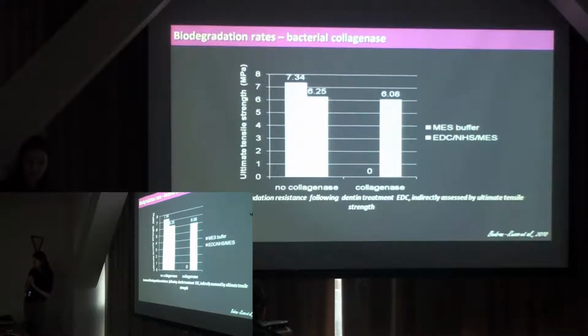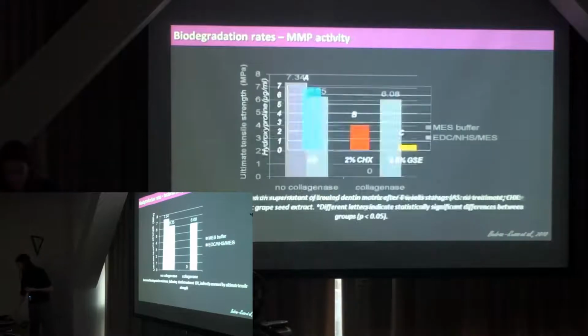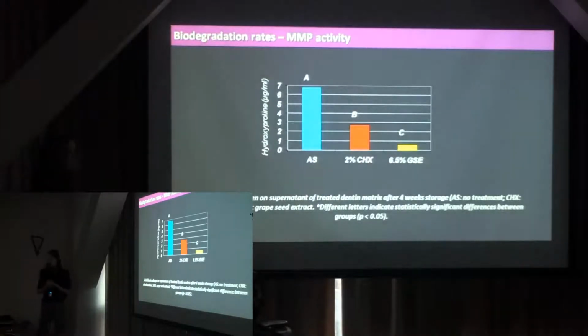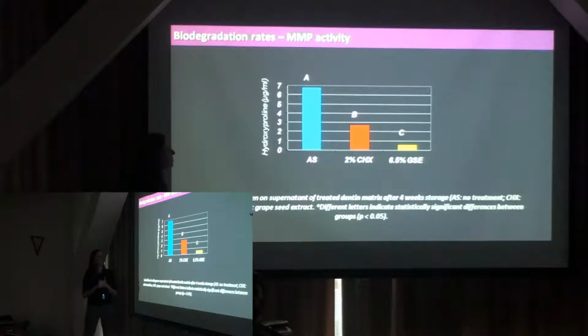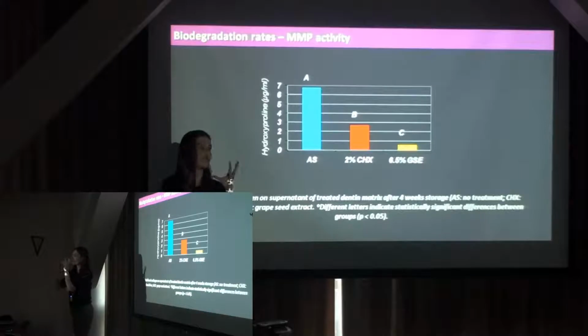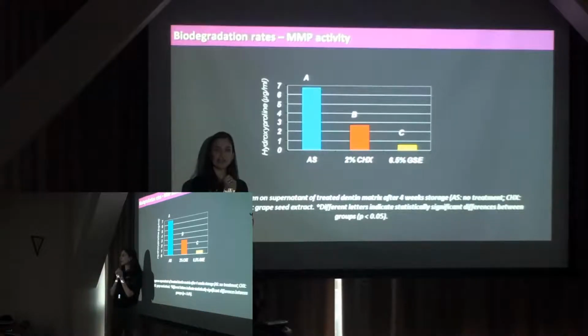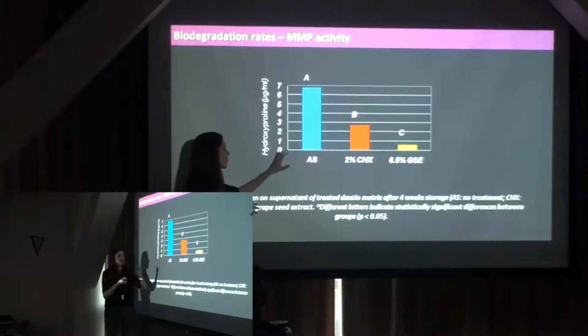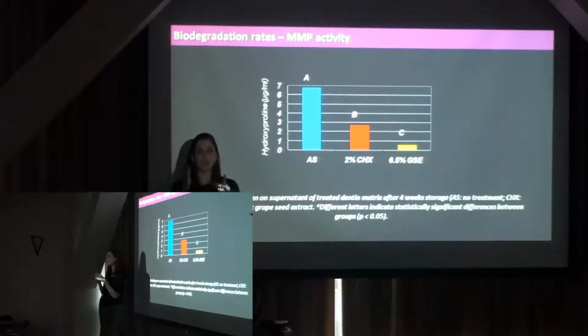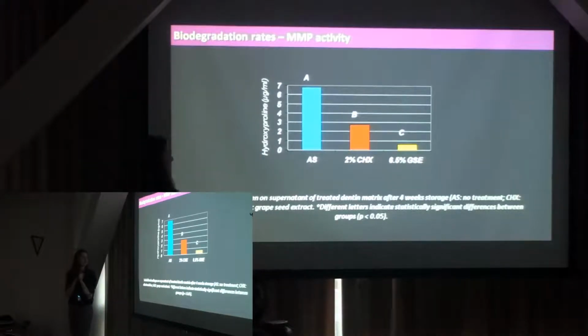Well, first we were more interested in the mechanical. We started looking into this ability, and the biodegradation is probably even more important than the strengthening of the mechanical properties because of this ability to stabilize it over time. This is where we talked about these MMPs. So what we do is we also use the same beams. We basically collect everything from one of our tests. We collect the supernatant, so the water that these materials were stored in, and we use a hydroxyproline assay to detect solubilized collagen in there.